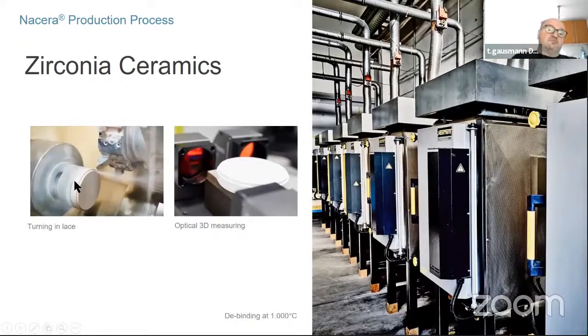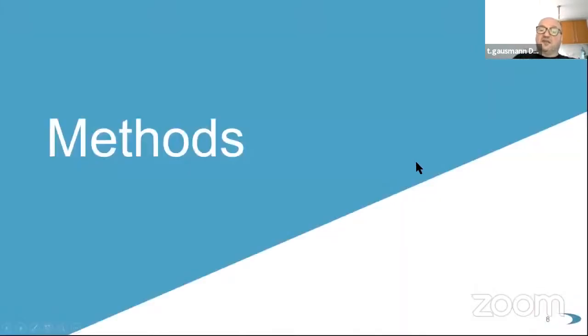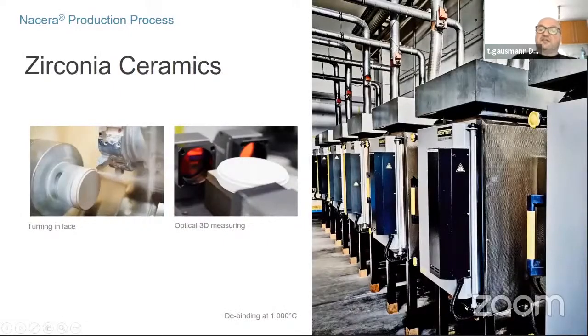We've got the turning at the moment. We are just thinking about changing this. We've got the optical 3D measurement, and there's another speciality. You can build an average. This is the furnace street where we make them. It's got a second side and a third side. These are 1, 2, 3, 4, 5, 6, 7 times 3. I think we've got 21 furnaces for dental. And in each of these furnaces, you can pack up to 160 discs for one pre-sintering at roughly 1000 degrees.